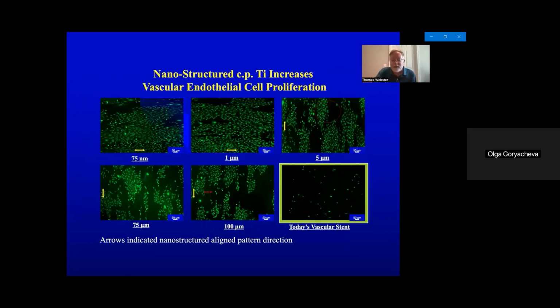If you don't do that and your stent remains open, and here's a picture of a stent that we used in an in vitro study with endothelial cells, and you see after 24 hours how few endothelial cells have attached. So all those open areas are prime spots for macrophages, leukocytes, neutrophils to attach to and basically signal through a chemical mediator that a foreign stent has been inserted, which could lead to inflammation or thrombus formation, basically buildup of plaque. Again, that you just tried to get rid of and push to the sides, you now have more plaque coming back because of these open areas.